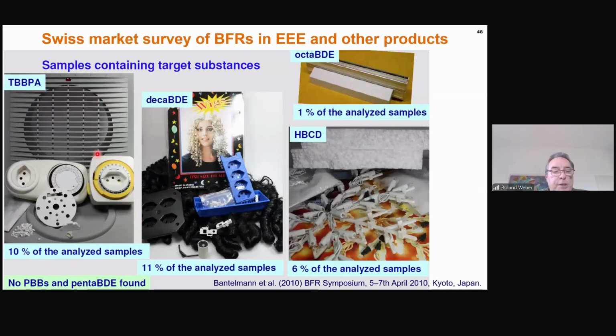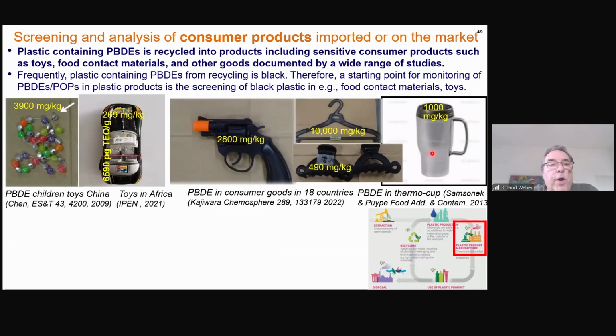So you see here, these are pictures from those products which contain DecaBDE. You see most of them are black plastic. Some of this here, but also tetrabromobisphenol A in different electric products, and hexabromocyclododecane here in electronic products, and of course in the polystyrene, expanded polystyrene. Then, very important are other screenings of the consumer market, like, for example, toys and food contact materials. So often in these black toys, or here you see this coffee cup with the black lid, you find PBDEs at low level, often below 1000 milligram per kilogram, sometimes above 1000 milligram per kilogram. And this shows that these have been made from recycling.